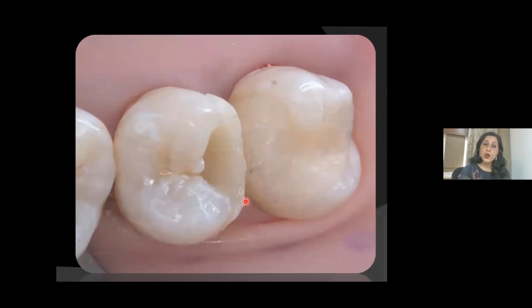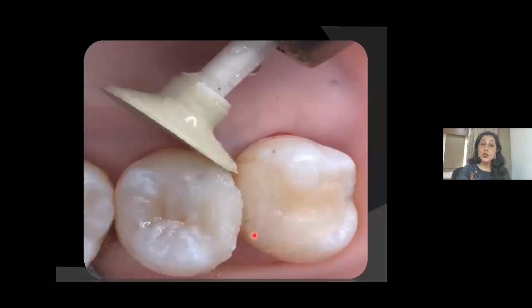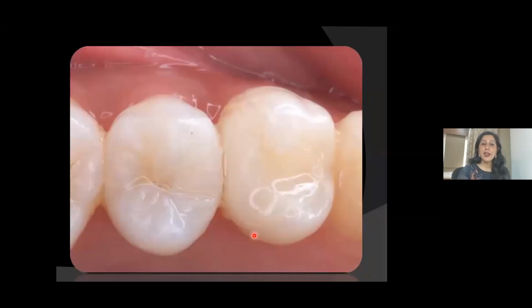light, and when you want your composite to shrink towards light, then it will seal this margin. So also remember to keep your probe in such a way that when the composite shrinks towards light, it seals the margin. Do not keep your probe in another direction like this and cure it. Otherwise, your composite will pull off from the margin. So these are little tips that you have to remember while doing the light cure restoration.